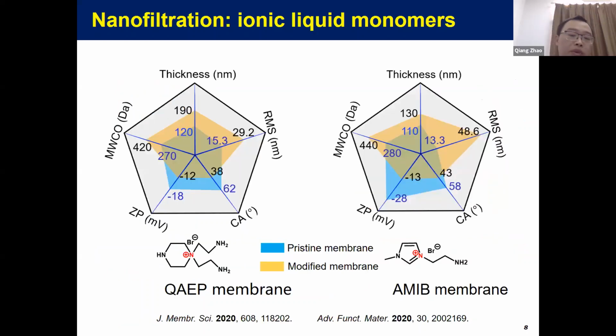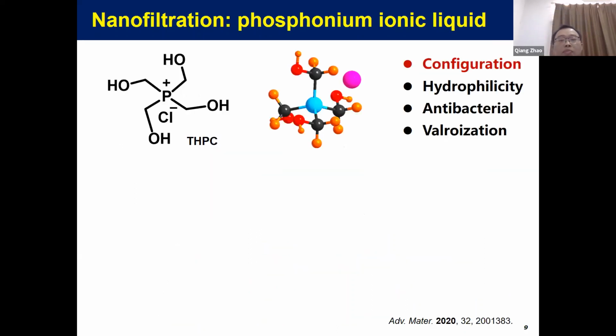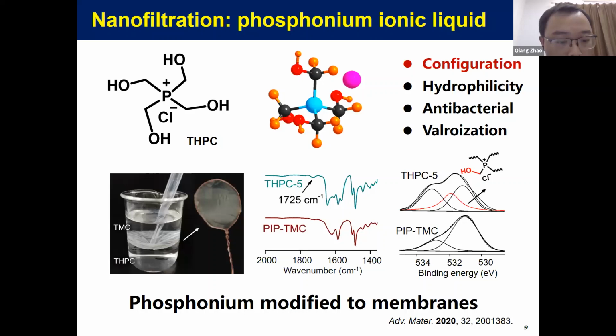What we are interested in, I will give you an example of how the structures changed after modification with these strong ion monomers. Basically, you will see the membrane becomes thicker, the roughness becomes larger, and the contact angle decreases, and more importantly, the mean pore size is increased. Let's take one of these monomers, for example, this monomer on the upper left corner, abbreviated as THPC. It is a monomer from the phosphorus industry, and the precursor for producing this one is hydrogen phosphide in industry. So it is very important to reutilize this monomer. And when it was put in the aqueous phase, it can react very quickly with the organic phase, forming a very thin film, as you can see from the photographs at the bottom corner of the pictures.